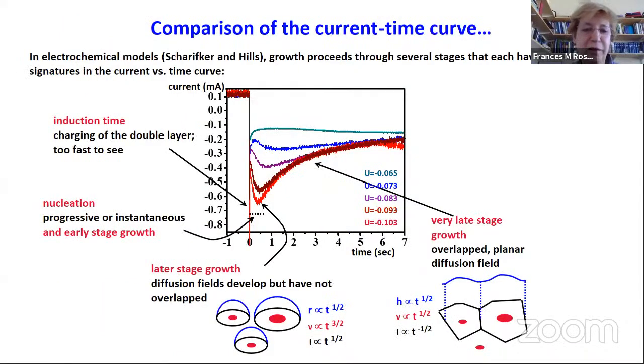Now, to illustrate how quantitative this can be, we can pull out all of these current time transients, and we can compare them with electrochemical models that predict that nucleation and diffusion limited growth should go through several stages. You have the nucleation of the objects. They could be progressive or instantaneous nucleation. There's some early stage growth going on. Diffusion fields develop, the growth slows down, and eventually at later stage growth, all the diffusion fields have overlapped and the growth rate of each object decreases even more. So this is what we expect from models. And indeed these graphs show what they ought to show in the models, but